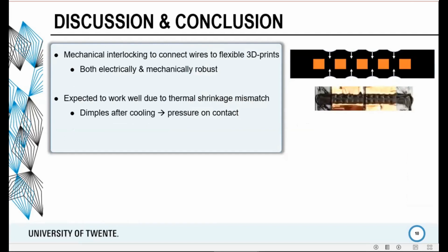All in all, we've shown that mechanical interlocking can be used to connect wires to flexible 3D prints, giving both electrically and mechanically robust contacts. And we strongly believe that the contacts work so well due to the mismatch in the thermal expansion of the metal and the polymer. Because what happens when you print, we print at 225 degrees Celsius, I think.